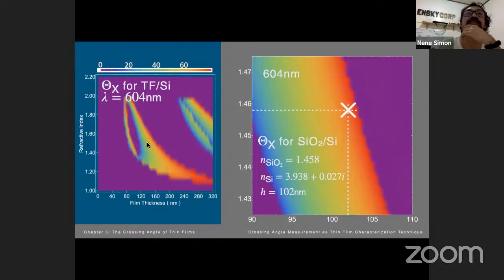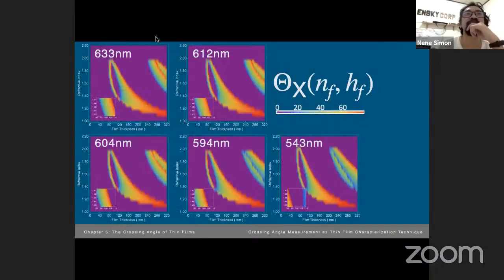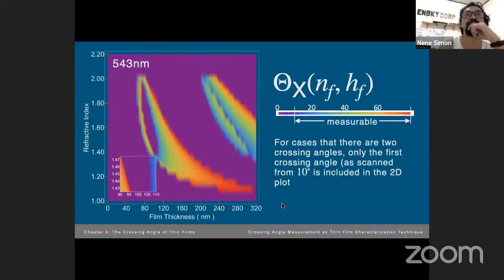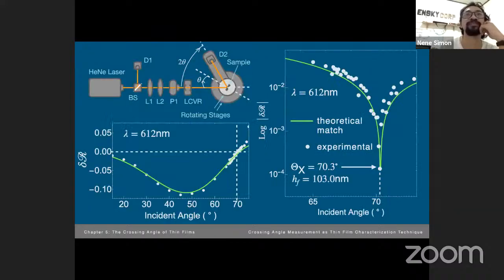If you change the wavelength, the bands move, as we see here, and for different wavelength, we will expect to have a different crossing angle value. So here is the summary for the 2D plot of the crossing angle for different HeNe wavelengths. For the case of the 543 nanometers, I'd just like to say that it has no crossing angle. So this is for the 543 nanometers. But for 633 and the rest of the HeNe wavelengths, we can measure its crossing angle.